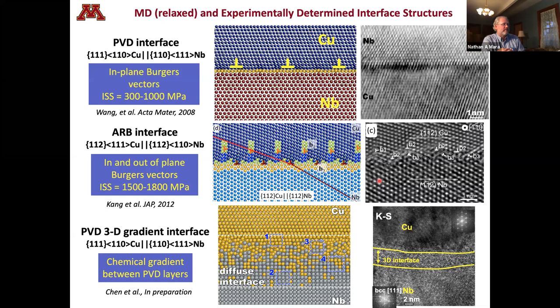So when you look at what we have here, it's the same orientation relationship and interface plane as what we had in the two-dimensional case. But instead of having this nice flat interface, which we can see in the 2D case, now we've jumbled it all up. And so by co-sputtering copper and niobium between the two pure phases, we've entered a whole new world of variables in what that structure can resemble.